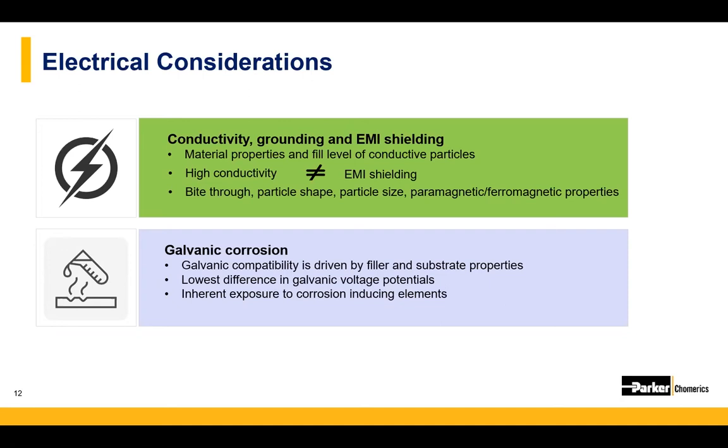And I want to repeat that for emphasis. EMI shielding is not always driven by the highest particle conductivity. While conductive fillers will have high EMI shielding, other properties that impact shielding are things like particle bite through, particle shape, particle size, and paramagnetic or ferromagnetic properties.